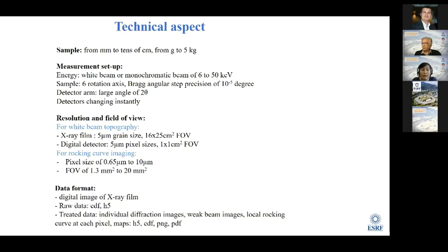And for the data, we can either have the digital image of the X-ray film with a very good resolution from microscope scanning, or for the rocking curve imaging, we can have raw data. It can be the old format of the ESRF, the EDF, or the standard H5 at the moment. And for the big data, after the analysis, we can give you individual diffraction images or the wide beam images, the local rocking curve at each pixel, and the map of the maximum integrated intensity or the peak position in H5, EDF, or even PNG and PDF format.